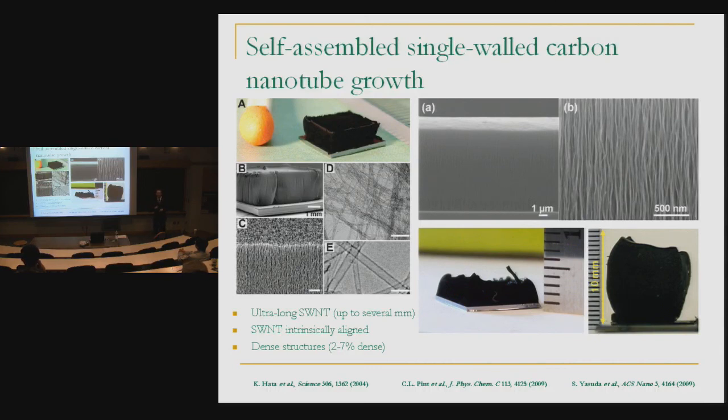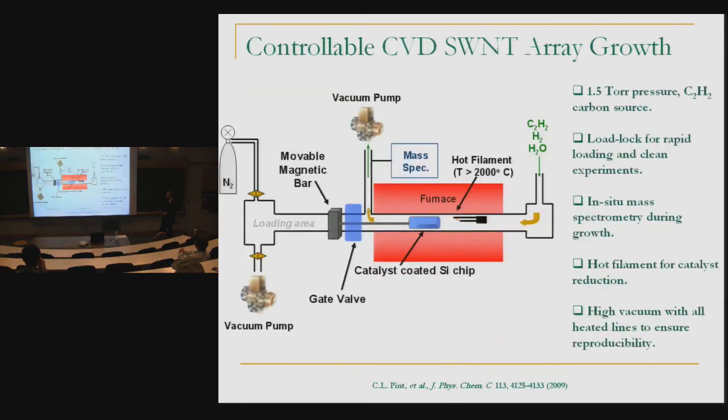And the idea is the iron has relatively high surface energy, so it's going to form a bunch of little small islands, which are going to be nucleation sites for nanotubes. And now when you grow these in a CVD system, or a chemical vapor deposition system, the nanotubes are going to interlock, and they're going to grow upward in a self-assembled nature. And the benefit of this type of material is that from this side to this side, it's one nanotube across, and it's this mat of aligned nanotubes. So this is a really exciting concept.